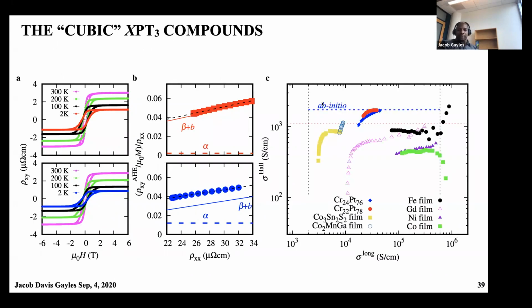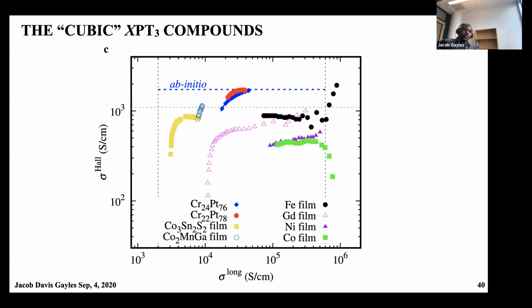What's nice is here we get this final plot, which I show at the end, which shows, again, the anomalous Hall effect versus the longitudinal conductivity, sigma XX. And here we just focus on intrinsic materials, and so here it is also only films that we're looking at. So what we have here in the orange is the cobalt-3 tin sulfide, we have the cobalt-2 manganese gallium, and we also have the iron, gadolinium, nickel, and cobalt elemental materials. I go to the next slide, which is just this slide here, this picture, just so it's enlarged.